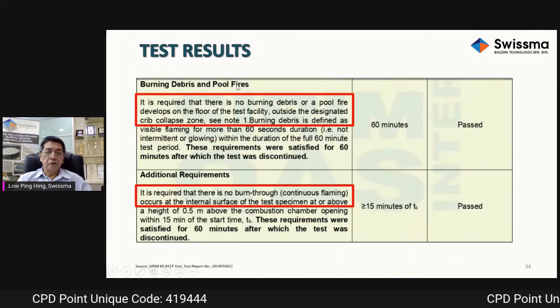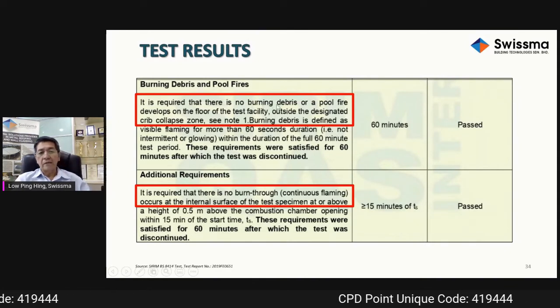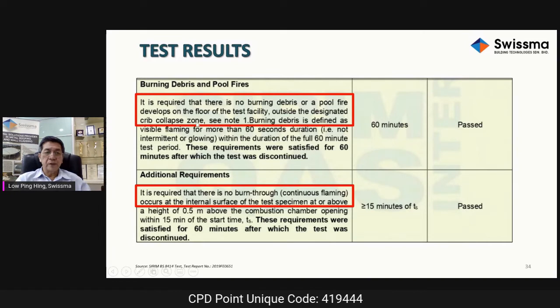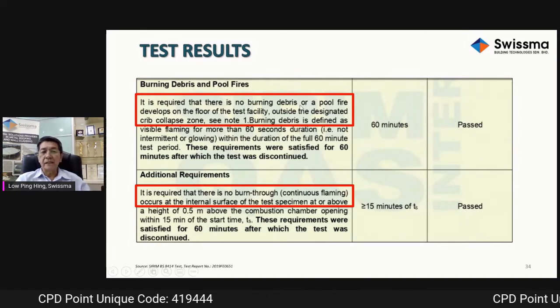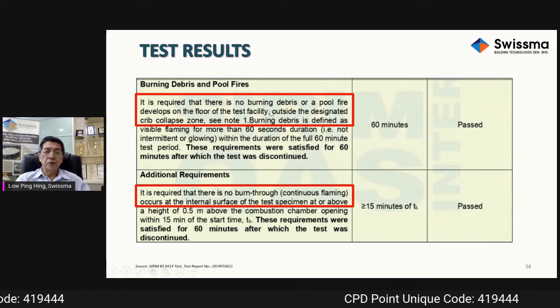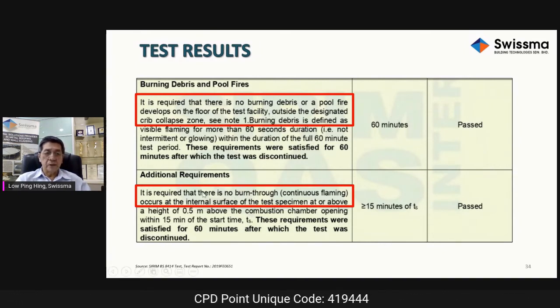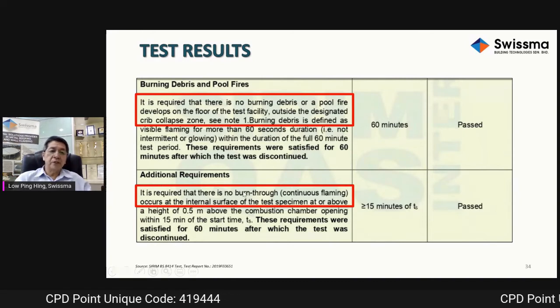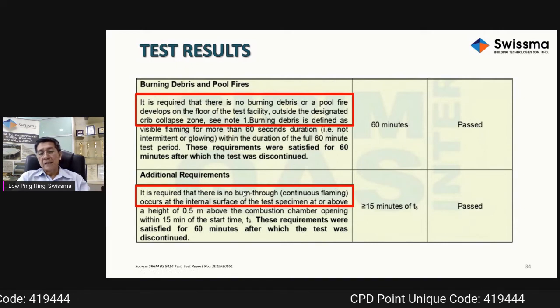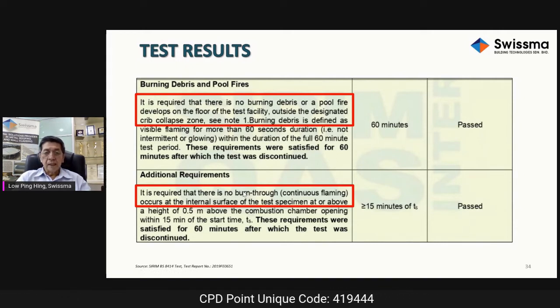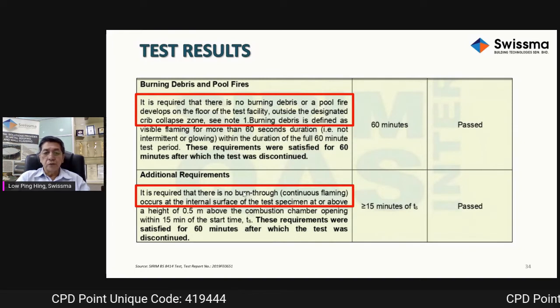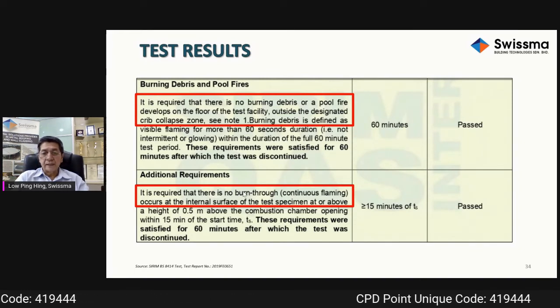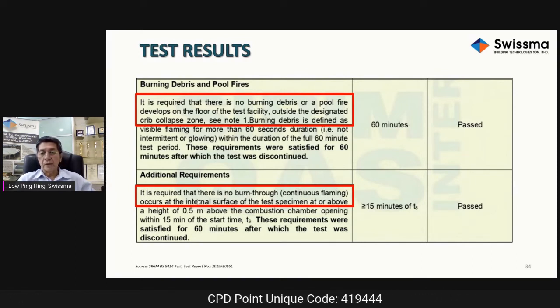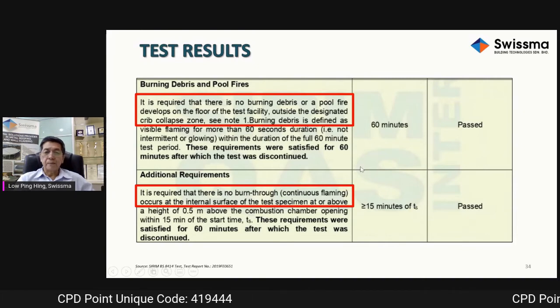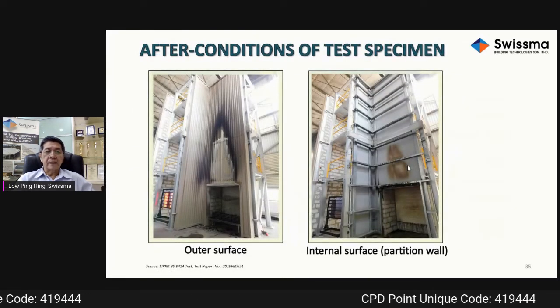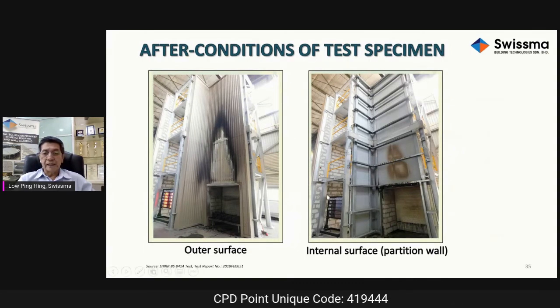Burning debris and pool fires. Again, this has to be falling outside the designated crib collapse zone. And in our case, none of these falls out of the zone. So we pass, and also there is very minimal debris falling onto the zone. This is the burn through. This additional requirement is for the part 2 test only, because part 2 assesses whether there's any burn through, in this case of the drywall system, and there was no burning through, so it passed. And overall, this test passed all the 6 criteria. And this is the condition of the test specimen after the test.